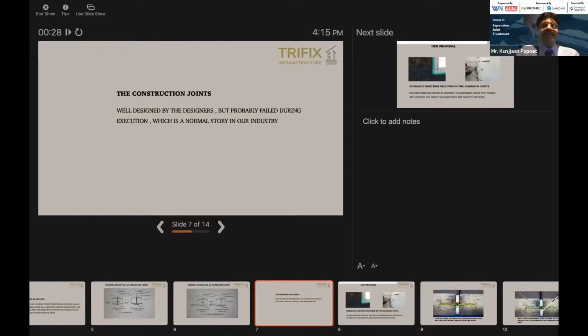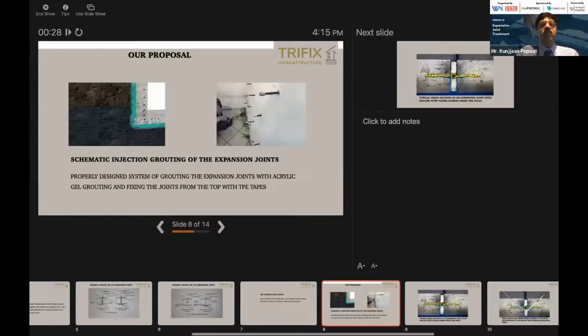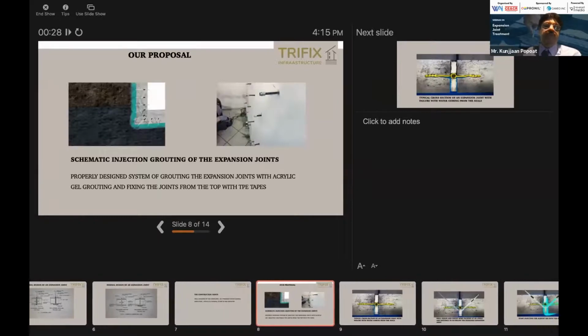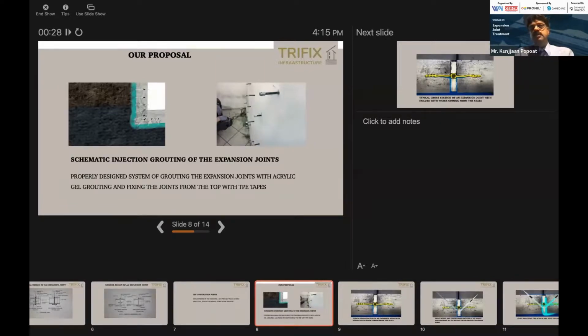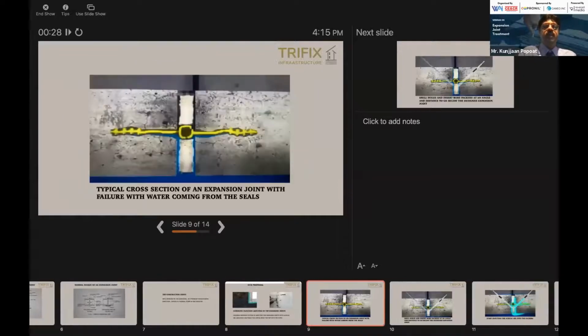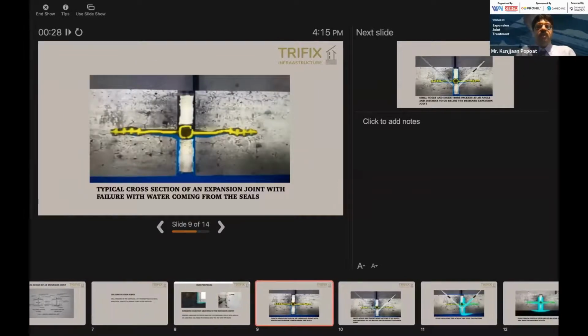After the study of the site and everything, we came up with this proposal. We came up with doing a schematic injection grouting of the expansion joints. And this time the grouting was from the top of the structure instead of from the bottom of the structure, which is what usually is done in expansion joints. This is a typical cross section of an expansion joint with the failure, with water coming from the seals.